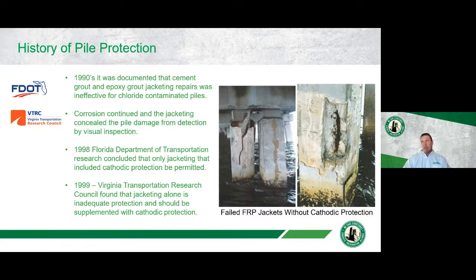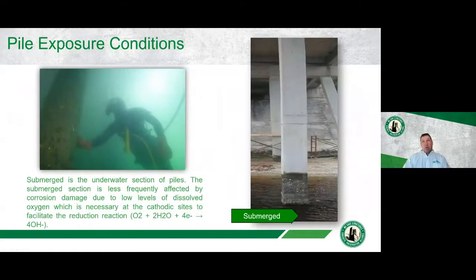So over here on the right side of the picture, you can see here this was an epoxy jacket, and here was a standard concrete fiberglass jacket, and you can see how the corrosion continued to occur. And by the time that you start to see this visual damage through the jackets, there's been a lot of corrosion and there's been a lot of damage that's been done to this structure. So now I'm going to go through and talk about the exposure conditions that these reinforced concrete piles are exposed to, and then I'll dive into some of the solutions or some of the cathodic protection jacket systems that are available for it.